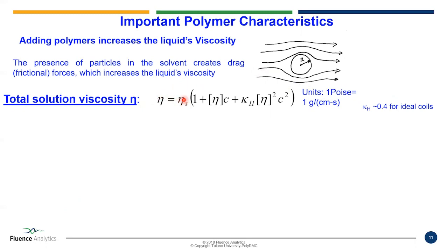That would be your pure solvent viscosity, whether it's water, oil, or honey. And as you start adding particles in, like polymers, it adds internal friction, because really viscosity can be conceived as internal fluid dynamic friction as well. As you add in a concentration C of these particles, you start increasing, usually, almost always, the viscosity of the liquid. And what determines how much it viscosifies is what's this here.